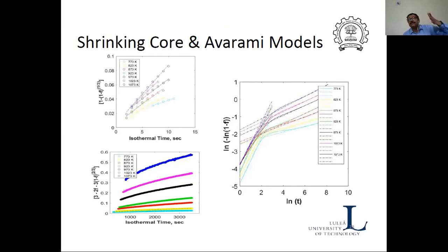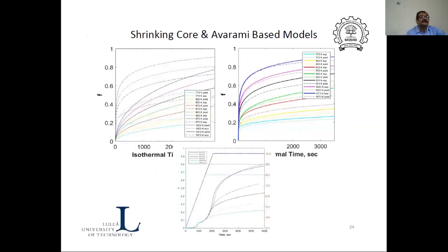That means we were going across different scales. One is the scale of the grains in the pellet. Then the pellet, where diffusion occurs, and at the grain scale, the phase transformation, or this oxidation, was happening. Again, we used the principles of diffusion, reaction kinetics, and conservation. All those things were used, and then we could develop models. So for example, this is the model versus experiments, which is a very good match. So that way we could quantitatively predict the oxidation, and we could quantitatively predict the sintering. So that way we studied the phenomena in isolation.